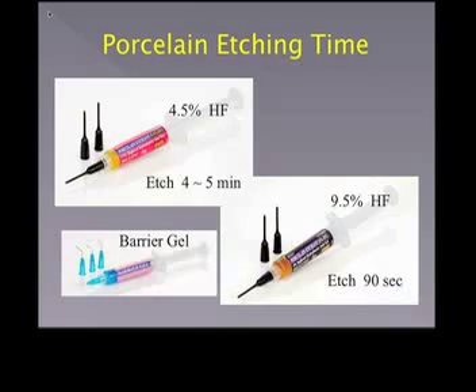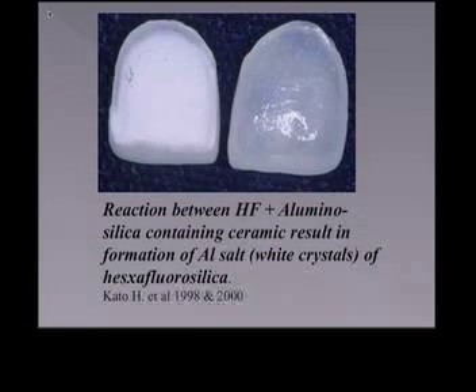But when we talk about these feldspathic and stacked porcelains that contain alumina, over-etching will create aluminum salts of hexafluorosilica. And what happens is that too much of that over-etching can create easy debonding. When you properly etch the surface, you create a really nice, strong bond.